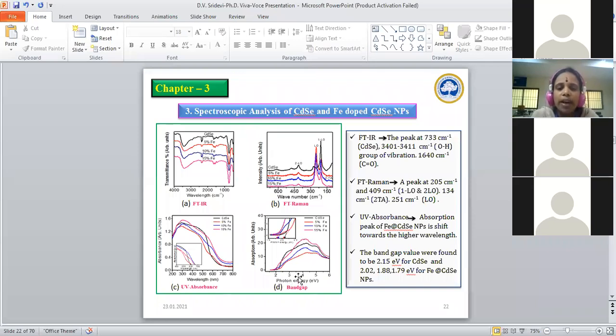Then figure D shows band gap determination of cadmium selenide and Fe doped cadmium selenide nanoparticles. The band gap values were found to be 2.15 electron volt for CdSe, and 2.02, 1.88, and 1.79 electron volt for Fe doped cadmium selenide nanoparticles, which shows the band gap values decrease with increase of crystal size.